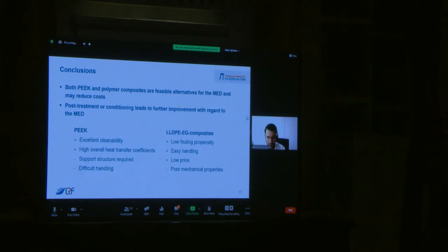The polymer composites, on the other hand, are very affordable, because of the materials polyethylene and graphite. And it is possible to extrude blades or tubes, which makes the handling easy. Nevertheless, the materials are not as pressure resistant as stainless steel.